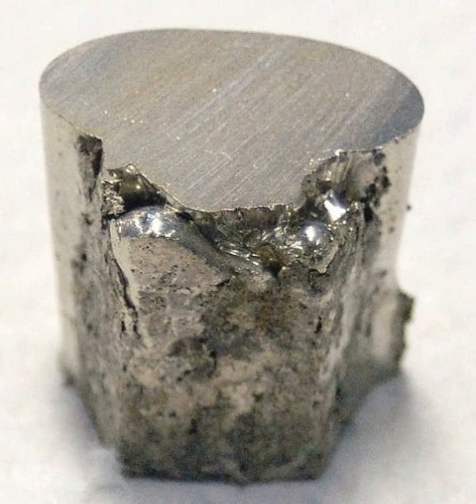Extraction and purification. Nickel is obtained through extractive metallurgy. It is extracted from the ore by conventional roasting and reduction processes that yield a metal of greater than 75% purity. In many stainless steel applications, 75% pure nickel can be used without further purification, depending on the impurities. Traditionally, most sulfide ores have been processed using pyrometallurgical techniques to produce a matte for further refining. Recent advances in hydrometallurgical techniques resulted in significantly purer metallic nickel product.